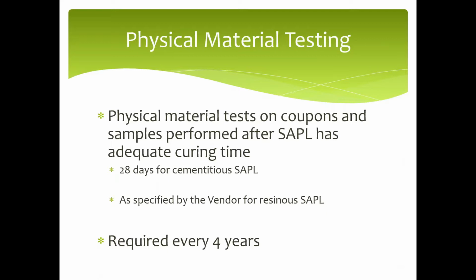All right, so the physical material testing, we call it 28-day testing, because that's the curing time frame that it takes for the cementitious material. It takes 28 days before they'll do any testing. So they'll make their coupons to whatever size is required by the ASTM or AASHTO test, wait 28 days of curing, and then they'll go do the test. For the resinous products, as we indicated before, the curing time is pretty quick. It's literally minutes in some cases. It's really up to the vendor itself. Most of the time it's pretty quick. They can apply it, wait about a day, and then go do the testing.